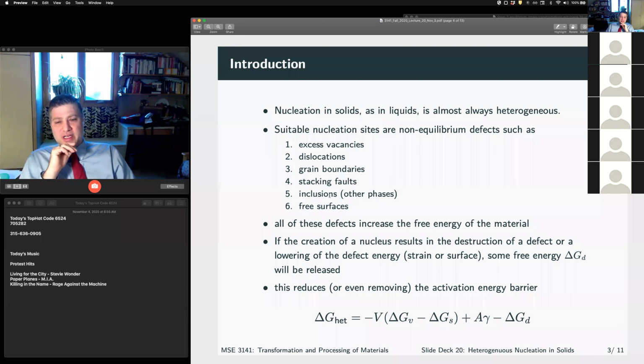Remember that we have a diffusional phase transformation here, right? So we're moving atoms long range, right? So we can eliminate a dislocation or a region of grain boundary area. And in doing that, the free energy associated with that defect is going to be removed from our system, and therefore we can reduce our activation energy barrier, right? So now we just have what we had for homogeneous, our bulk free energy term, our strain term, our surface energy term, and now we have a reduction due to the defects that are being removed.